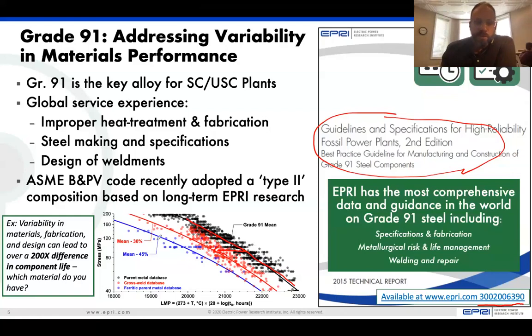If you improperly heat treat grade 91 steel, you may get to this lower bound curve, which can have between the highest performing material and the lowest performing material almost a 200x difference on life. So a component that would have lasted over 1 million hours may not even last 5 years in your power plant. So it becomes critical that you take into account these aspects as you continue to build more power plants, and as you begin to manage the life of your existing power plants. Knowing what material you have is absolutely critical.